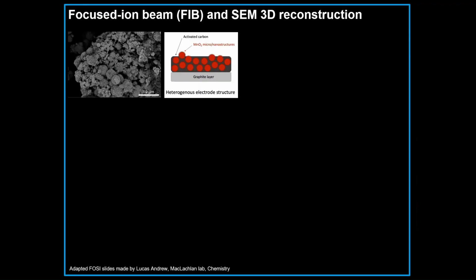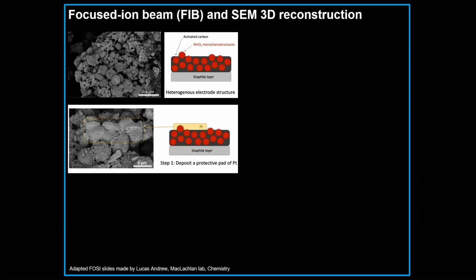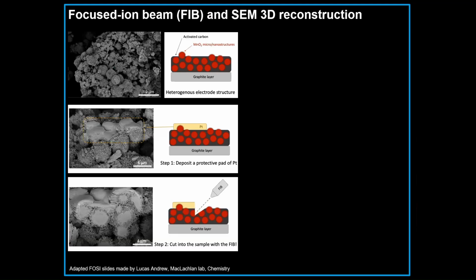samples. Here we have the electrode structure made of graphite layer and manganese oxide particles embedded in activated carbon. And with these samples, we deposited the platinum pad on top of the samples, and then did FIB milling. So you can see the internal structure of the samples. Here is the platinum pad, and here is the nanoparticles here. You can see.